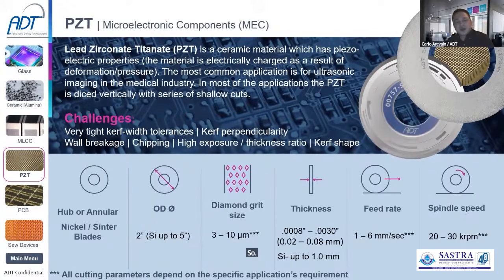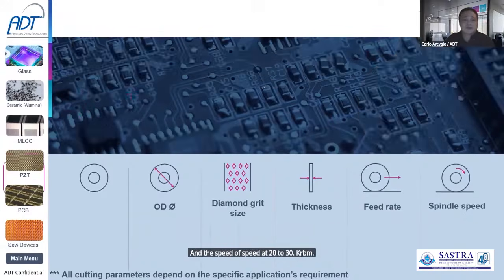What was mentioned here is that the tight tolerances are dependent on the blade straightness. The pitch of the cut line is also very tight. So the straightness, the balance of the blade, and its ability to cut straight is the main thing for this particular application. Nickel is a very good blade to cut straight and to have very stiff strength, so nickel is a very reliable blade for this application. The diamond grit size range is 3 to 10. Thickness range is shown here. Feed rate is very slow at 6 mm per second, and the spindle speed is 20 to 30 kRPM.